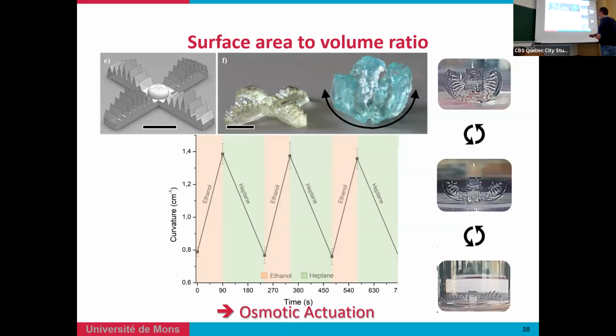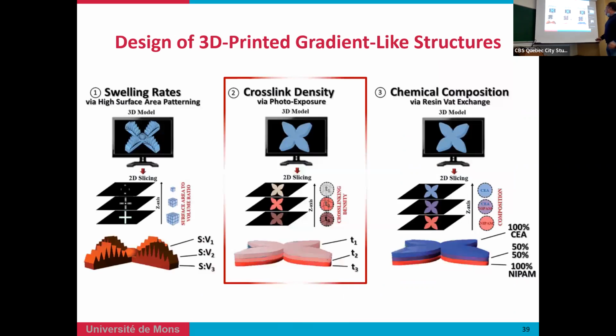We do a cycle, immersing in a good solvent, ethanol in this case, then a bad solvent, heptane, etc. By following the curvature, the deformation based on the angles we obtain, we can show that our cycle is reversible. You get the same position after doing this several times, based on this osmotic effect.